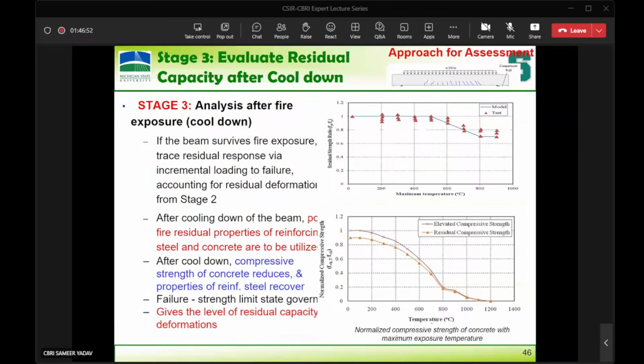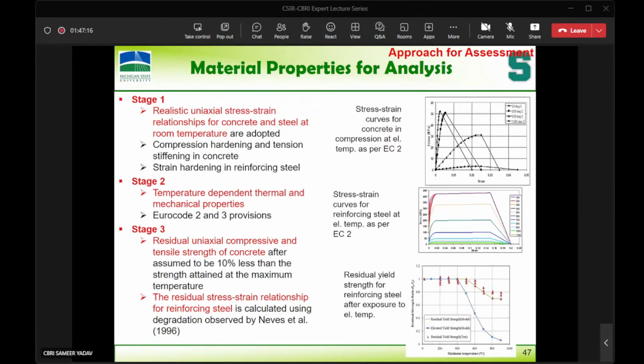Stage 3, after the fire exposure, what properties do you need? These are called residual properties. Basically, what are the residual properties? You heat the specimen, leave it to cool to room temperature for 2 hours, and then you test that cylinder, that's the residual. During fire, it is like the heating phase. When it is still burning, you test it, see how much strength it takes, and develop the stress strain relations. So at each stage, it's a different set of relations you need to use: stress strain curves as well as thermal properties in stage 2, and residual properties here.